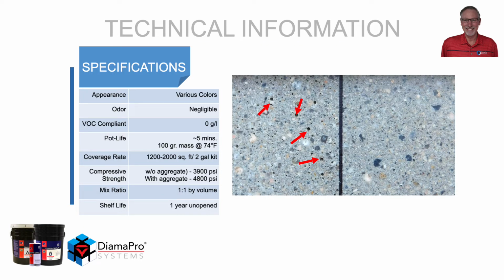The material comes in various colors. The odor is very slight. The VOC content is 0 grams per liter. The pot life is approximately 5 minutes in a 100-gram mass. So what that says is do not leave it in the container for very long without putting it on the floor. The coverage rate is anywhere from 1,200 to 2,000 square feet per 2-gallon kit, which equates to 600 to 1,000 square feet per gallon.